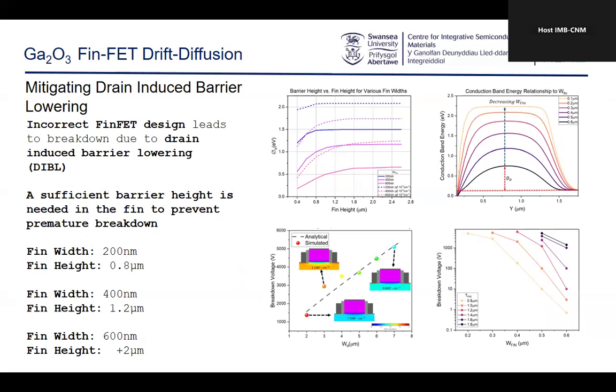Okay, and we also looked at similar effects, right? The drain-induced barrier lowering in gallium oxide. All right, same effect as it is in silicon carbide. But you can see here that for smaller fin widths, you get a much higher barrier height and it's much more likely to be normally off, which is advantageous here. Okay, I think I'm running over time, so sorry.